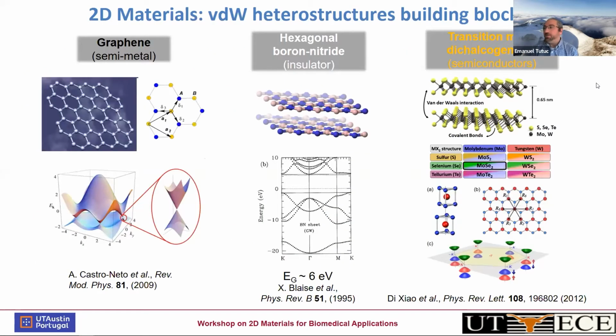So 2D materials, this is a very brief overview. They've been discussed quite extensively already in this conference. We have graphene that consists of carbon atoms in a honeycomb lattice. It's a semi-metal with a relatively high mobility. A peculiar property of graphene is that it has a linear energy momentum dispersion that is illustrated here. Okay, and it has a Brillouin zone that is similar to the direct lattice. It has a hexagonal unit cell. The corners of this Brillouin zone are typically referred to as the K points, and that's where the band minima are in graphene. And in proximity of these K points, there is a linear energy momentum dispersion that departs, for instance, from the prototypical quadratic energy momentum dispersion that we would see in a gap semiconductor.